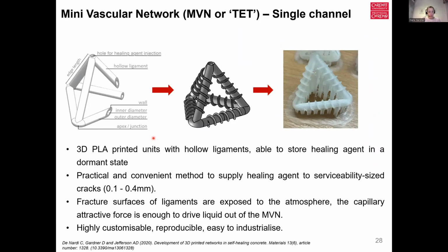We have the fracture surfaces of the ligaments. When a crack intercepts two of the ligaments, the healing agent is obviously exposed to the atmosphere, and that provides sufficient attractive or capillary driving force to take the liquid out of the minivascular network. These units are highly customizable, reproducible, and hopefully easy to industrialize, although that is one of our current challenges. These units themselves are about 40 millimeters ligament length, and they have an internal diameter of 5 millimeters and a wall thickness of 0.5 millimeters.